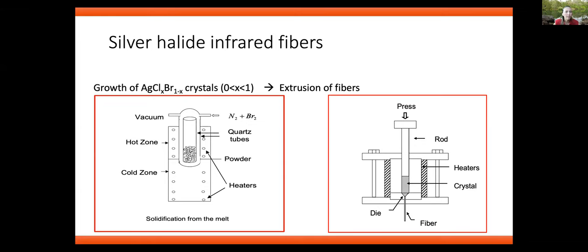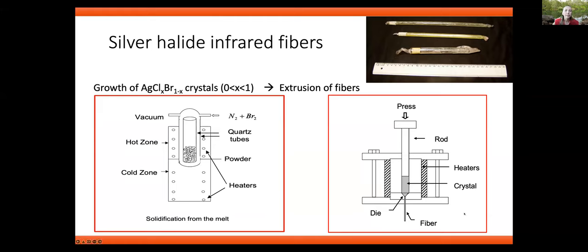The way those fibers are made is by growing the crystals inside a chamber, inside quartz tubes with a heater around them. Then they grow over time and solidify. And then to make the fibers, an extruder is used. So you just push the material out through a small hole and an optical fiber comes out. This is an optical fiber of only the core. There's no cladding on top of it. And here are some examples of the actual quartz tubes with the material, which has a yellowish color. So we've used those fibers in our work to develop some sensors from them.